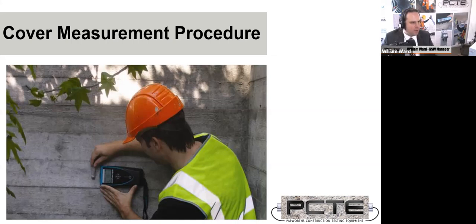Now, a couple more cover meter questions. We had Will asking, if the mesh is only locational tack welded and not proper 50 millimeter long welds, will that still affect it so much? I actually don't know the answer to that. What I'd suggest is you could experiment a bit. And to add to Nat Cox above, if we have a fully welded 60 mil bar cage, how much would that affect the cover measure as opposed to a tied cage?